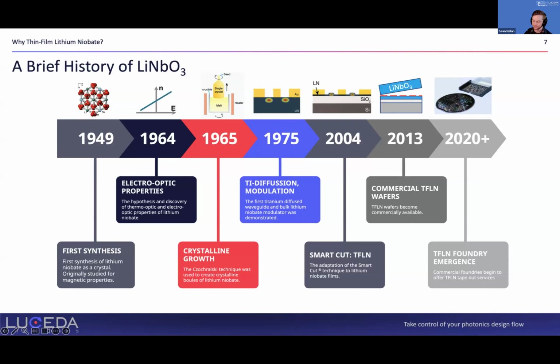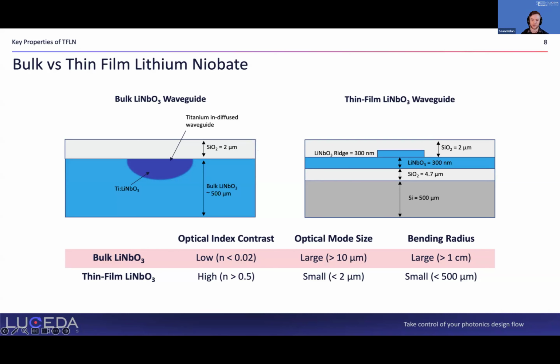So how do we bring the beauty of lithium niobate into a PIC? Well, we create these thin films of it. On the right here is a thin film lithium niobate waveguide cross section. At the heart of it, the thin film lithium niobate layer is bonded to a silicon wafer with a molecular bond, and I'll go over that again in the next slide. But this gives us the ability to densely integrate these devices onto a chip. Our waveguides are smaller, with tighter bending radii, so we can make PICs out of this, and we can incorporate other components.